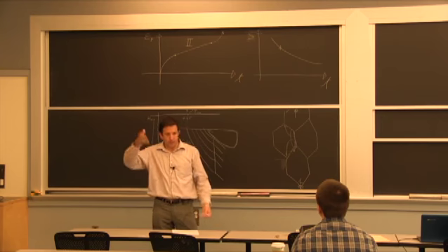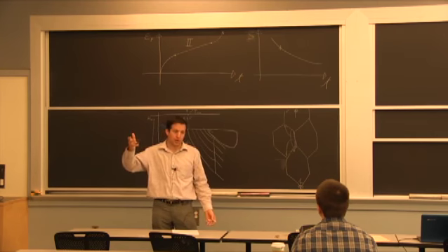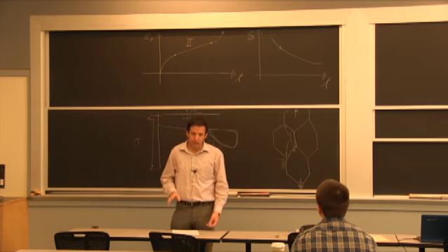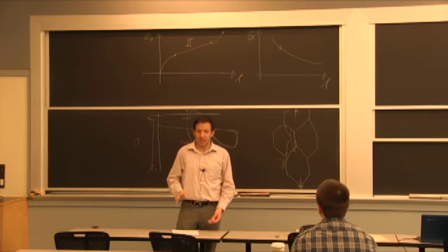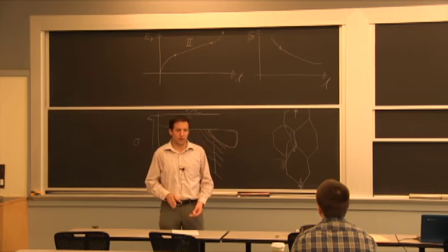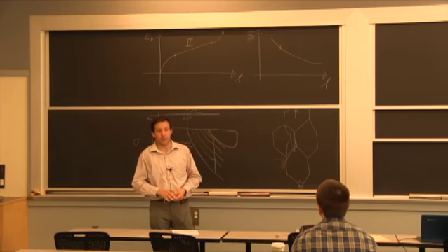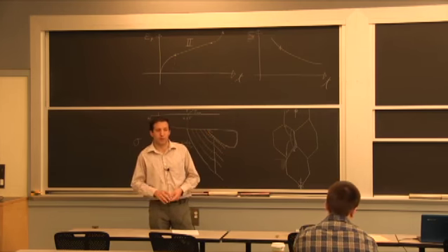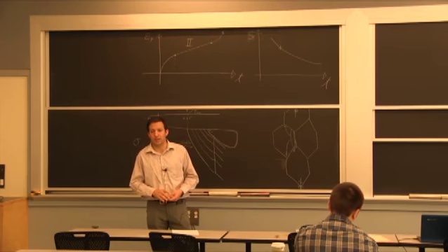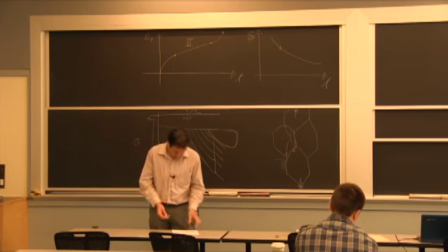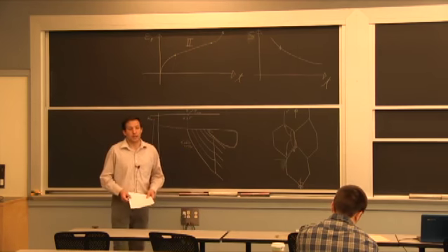And that's why you get a permanent deformation and a permanent elongation. The only thing that remains more or less the same is your density of dislocations. So you don't have any hardening anymore. That's why you keep deforming over time. If you had the hardening we have at ambient temperature, everything would stop. Good question. Anything else?